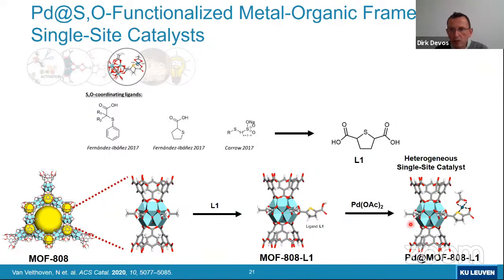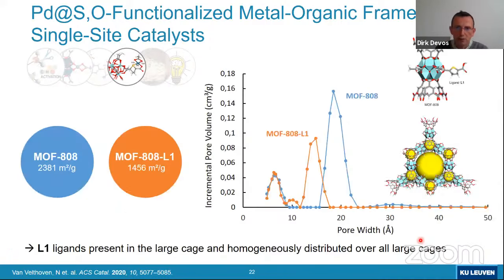And that's precisely what we did. So we actually used now the MOF not as much as a support itself, but as a platform to dock ligands upon. Yeah? And then you get this type of situation with the palladium now docked on the thioether carboxylic acid, which is itself attached to the MOF surface. Yeah? You can give many types of physical-chemical proof that this is indeed what happens if you do this type of modification of a material like MOF-808, but just one to show you, which is like the real physical proof, that's a porosity measurement.